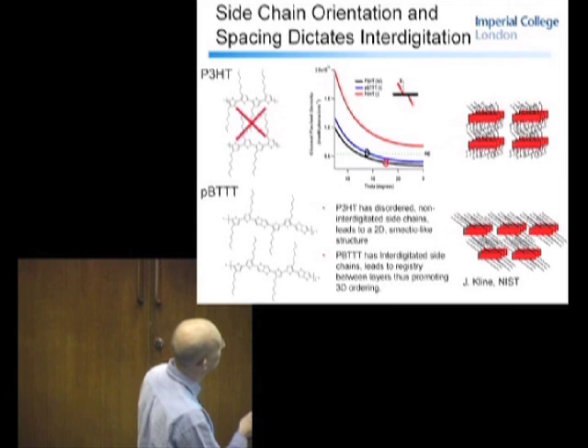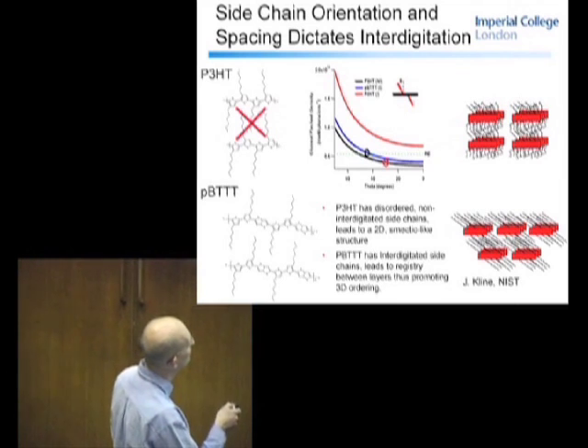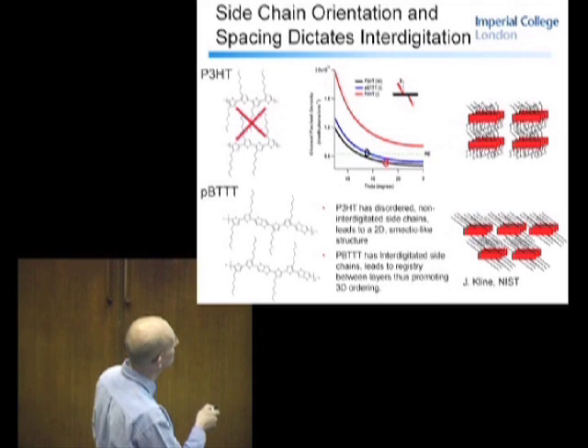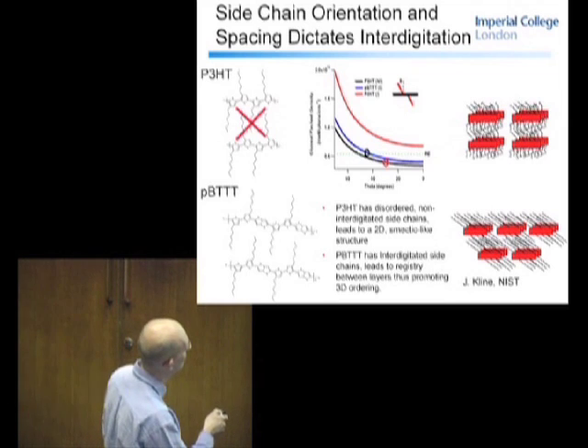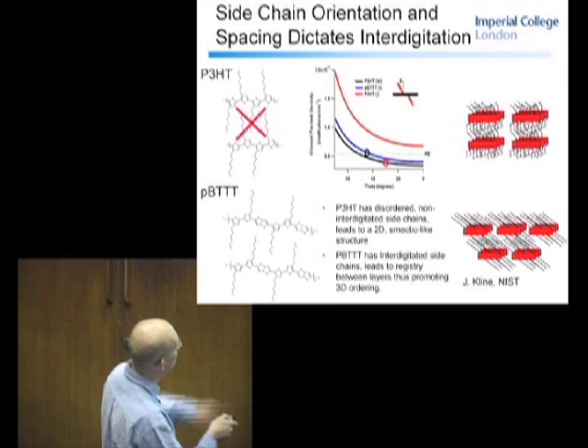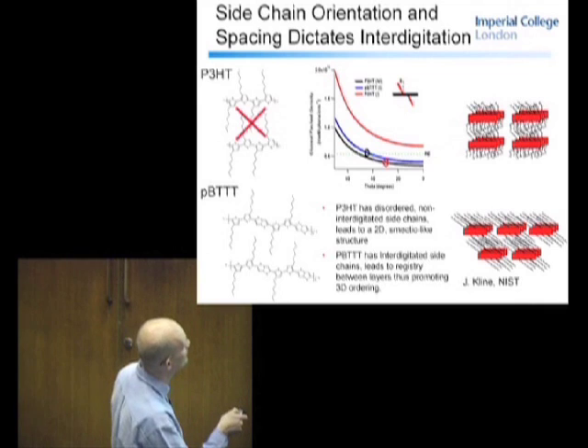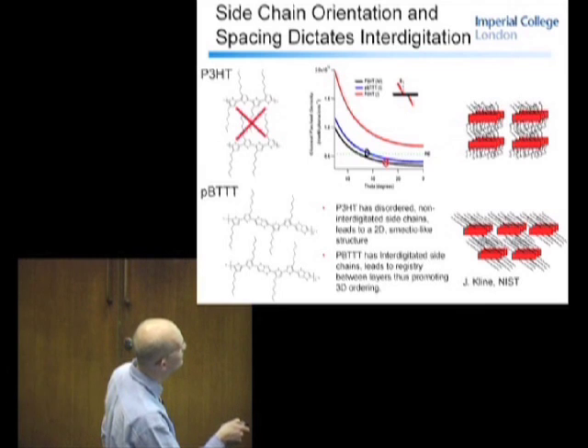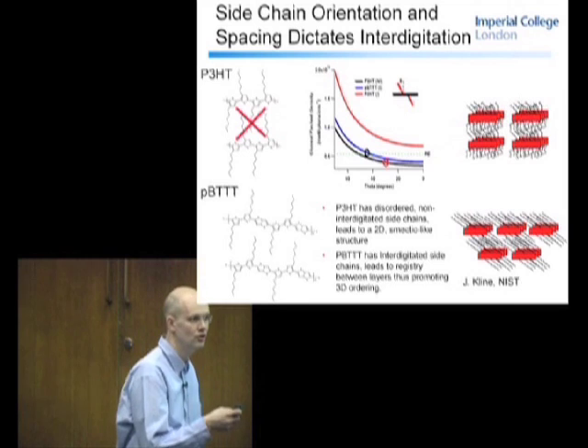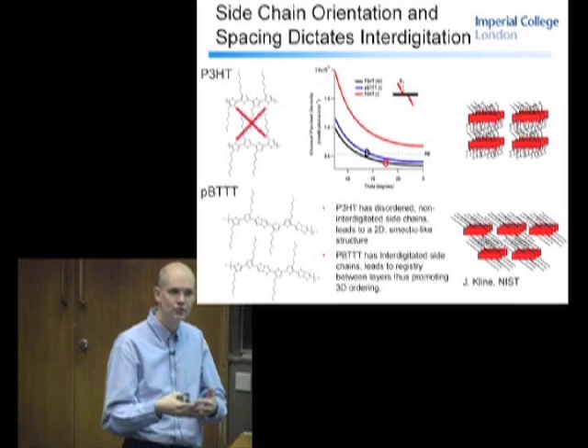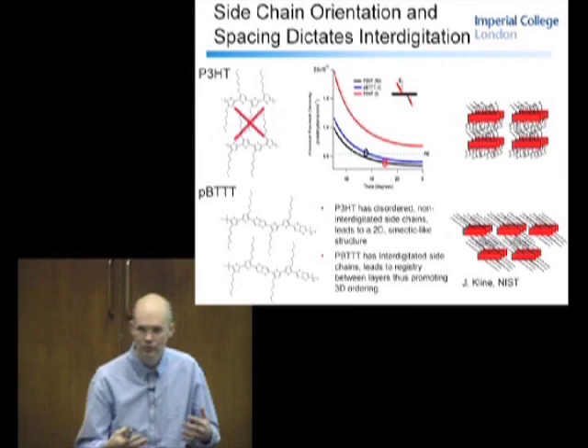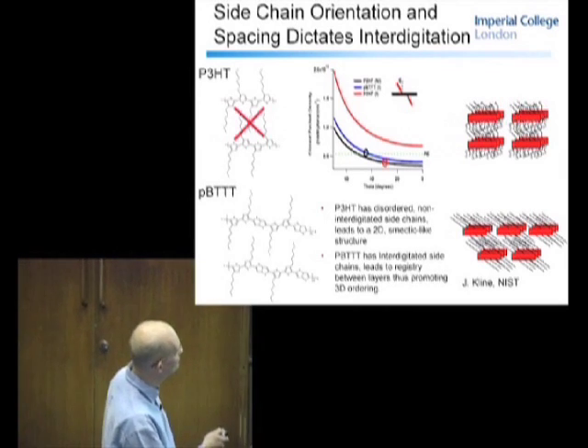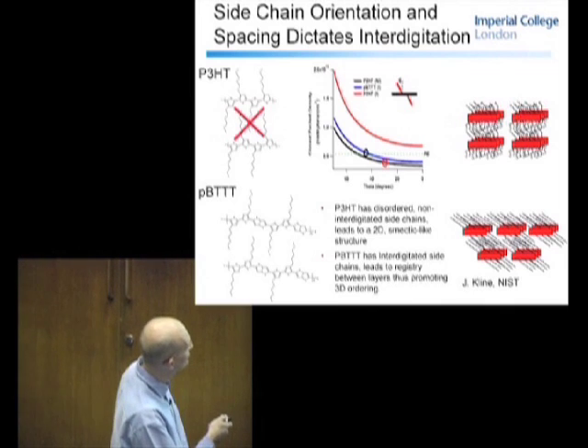What you see is that no matter what the angle is, if you go to 0, so this would be normal to the backbone, and 90 degrees would be in the same vector as the backbone. You see here, of course, as the side chain folds down, the density becomes even higher. But even when they're fully extended, the close packed density here is higher than the density you can calculate from crystalline polyethylene, which is probably about as dense as you're going to get for alkyl packed chains. So it's very, very unlikely. Whereas in the case of the blue here, it is PBTTT.